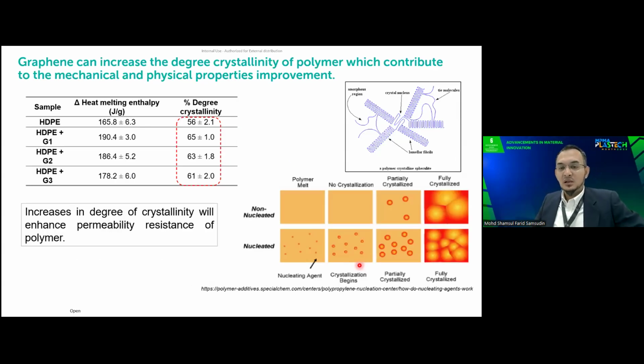And other than these barrier properties, we also evaluate how this graphene affects the crystallinity of the polymer. For this case, we evaluate on HDPE with different types of graphene, G1, G2, and G3. And we notice from this study, with G1, the finer grade of graphene, it can further improve the degree of crystallinity. And it proved from this work that graphene also can act as a nucleating agent to improve the crystallinity structure of the polymer. And from there, it will improve further other properties like the barrier and also other mechanical properties.